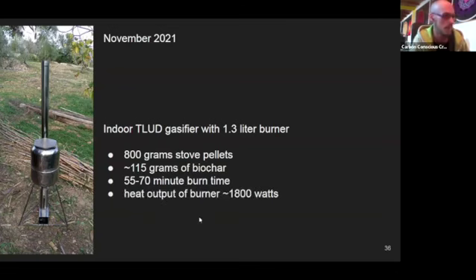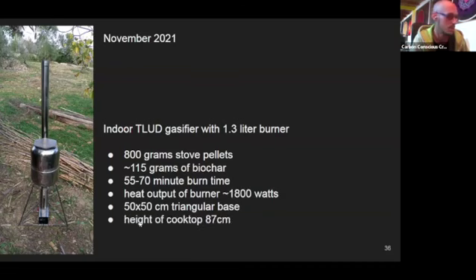So the heat output is roughly 1800 watts. There's a 50 by 50 centimeter triangular base. The cooktop has a height of 87 centimeters, which is quite convenient. And it uses 80 millimeter flue pipes, which are widely available. It's the same type of flue that conventional pellet stoves are using.